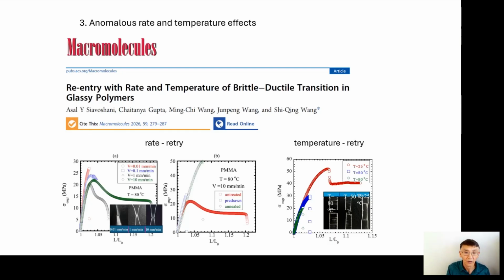Same with temperature. Temperature usually, by definition, as I reviewed for you, as you move to higher temperature, you tend to achieve ductility from brittle to ductile. But we found if you further increase temperature, this ductile polymer can turn brittle. No way any conventional classical understanding could rationalize, make sense out of this. But read this paper. It explains why this can happen.